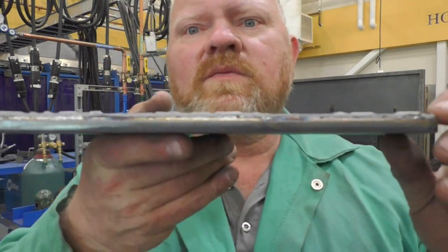The toughness of the material, and whether the weld has a flat face, a convex face, or a concave face, all matter. Stainless steel, 309 will tend to tear hard. It's tough, but it's the root that you're looking at. Okay, so if I look carefully at this root, what I have here basically is this fused into that edge. There's no real deep penetration, but it basically fused into the edge.